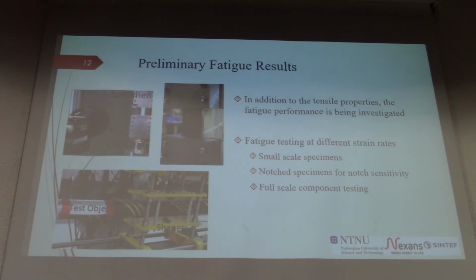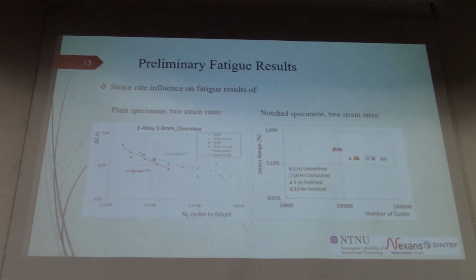Also, we have run different kinds of fatigue tests, that is on plain specimens, so without stress intensification, and notch specimens. Here there is a small notch that has been made to simulate the presence of a defect or hard particle introduced during the production of the cable, and then full-scale bending tests. What we have found is that there is clearly a dependence of the strain rate on the fatigue life of the material. And so in this case, this curve is made at 10 to the minus 2 and 10 to the minus 3 seconds to the minus 1 strain rate.